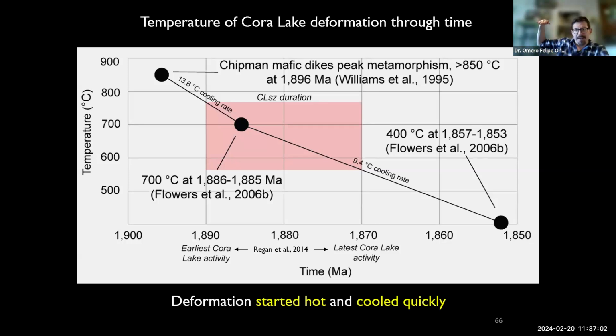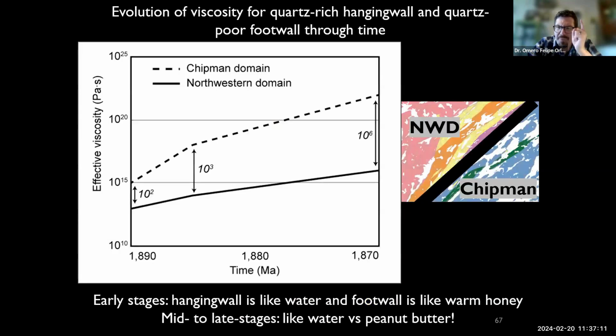So we have this really, really high temperature event, and then deformation starts, and then it sort of just cools rapidly throughout deformation. And this is really important because thanks to those squirrely flow laws that I'm not going to explain much more, you can basically say, okay, look, when this shear zone started deforming, the whole region was quite hot, right? And the difference in viscosity between the plagioclase-rich wall and the quartz-rich wall was not that much. 2 orders of magnitude. Who cares? That's like water and warm honey, right? That's not a big deal at all.